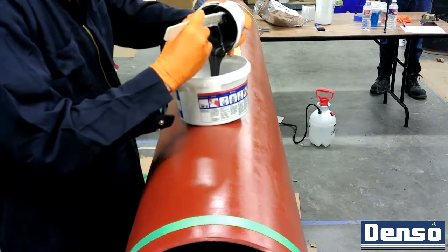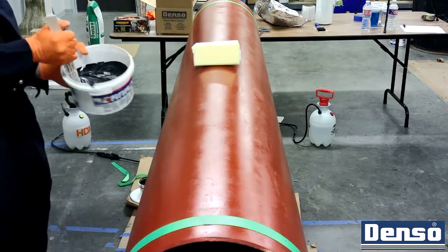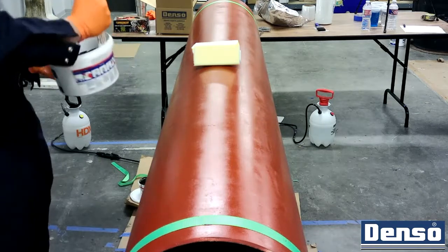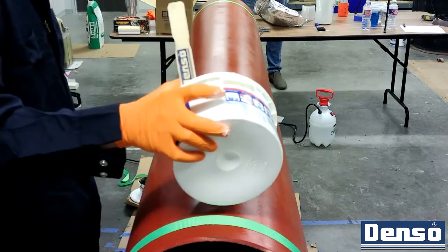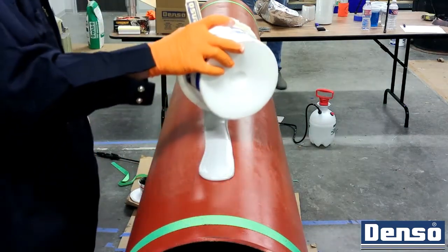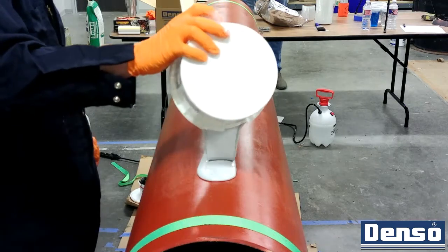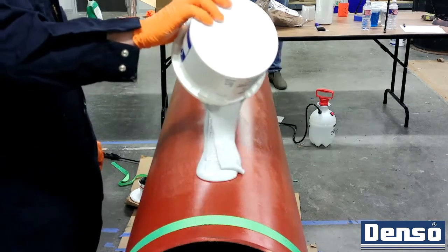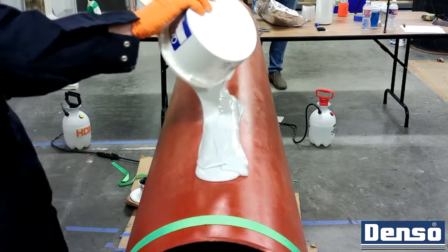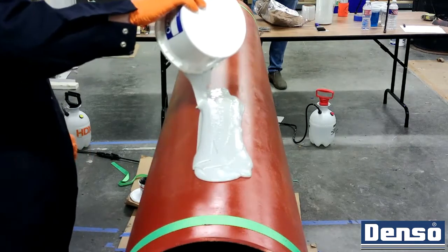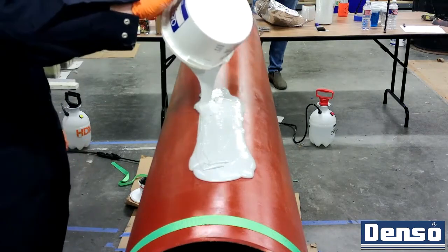For mainline applications, it is sometimes unfavorable to perform surface preparation along the entire length of the pipe that will be protected. When sanding or roughening of the existing coating is not feasible, it is recommended that the leading 3 to 6 feet of the pipe string is sanded to provide an anchor for an epoxy primer to bond to the surface.